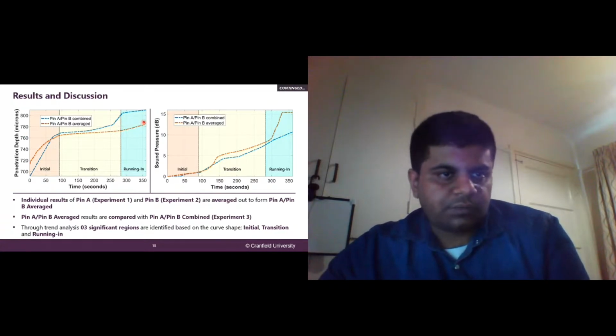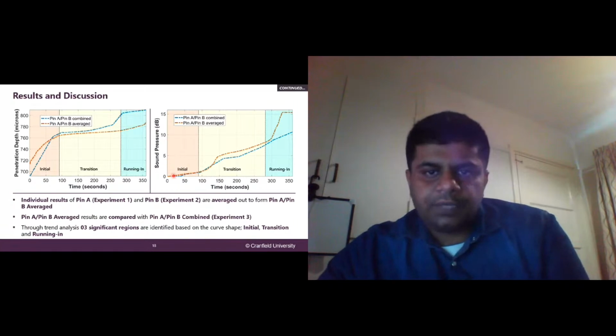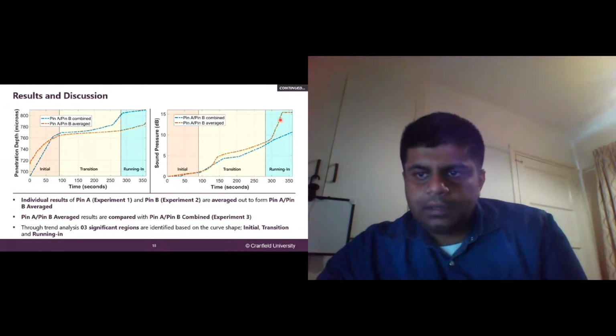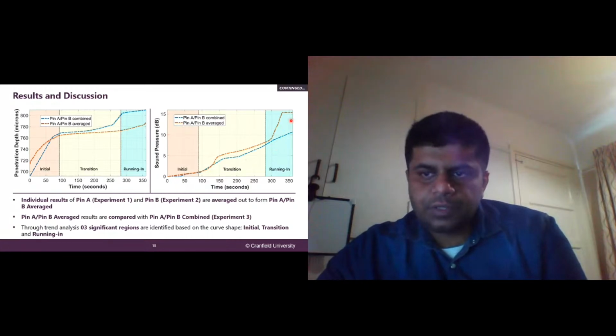Or okay, slightly more than that. And if you look at the sound pressure, again, this is in good correlation, except for this spike in the running in region, which can be averaged out as well at this point. Again, this is not really a significant sound pressure difference. The overall trend shows a very strong correlation between the two graphs on its own.